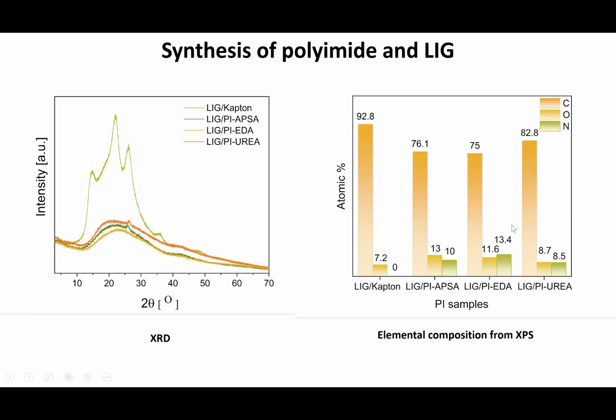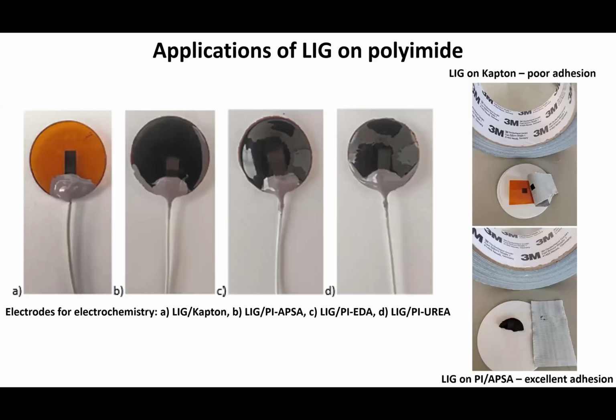We can measure the elemental composition, for example, from XPS. We see that these are all highly carbon containing. They contain some oxygen, even as LIG on Kapton does. However, our designed and synthesized polyimides contain nitrogen, which probably dopes the graphene and yields these low sheet resistance electrodes. We did make electrodes from all of these, and we performed some basic electrochemistry measurements, but we're just in the phase of analyzing that, and I don't want to show anything conclusive at the moment. But they do act well for electrodes.